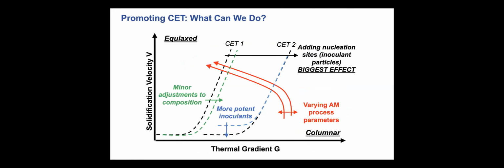So with respect to this columnar to equiax transition, what knobs do we have available to us to impact microstructure development in additive manufacturing? So we have solidification velocity versus thermal gradient. Again, we have these CET curves, and as shown here in green, we can make some adjustments to our alloy composition, and that'll shift our CET curve. Another knob we have to turn is obviously varying the AM process parameters, or the GV conditions that are experienced in the melt pool, as shown here in red.